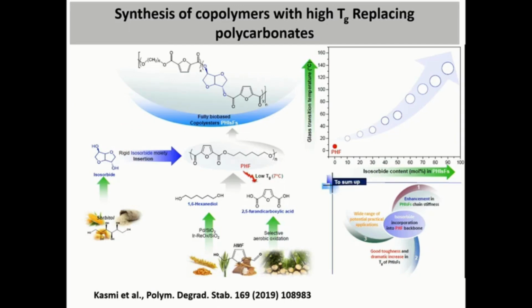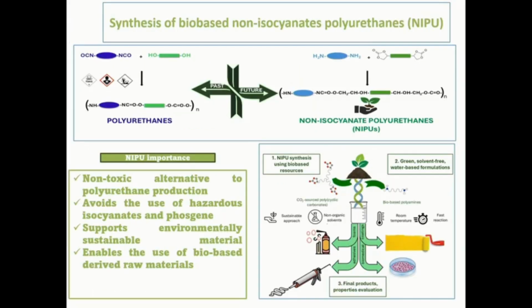Also here, you can see some attempts in our lab to produce high glass transition temperature polymers in order to replace polycarbonates, especially those used for water bottles, because you know very well all these polycarbonates are produced using bisphenol as monomer, which is very toxic. Here we have been using isosorbide, and you can see that the glass transition of the copolymer was increased substantially in all cases, reaching the level of 140, which is very similar to that of polycarbonate.